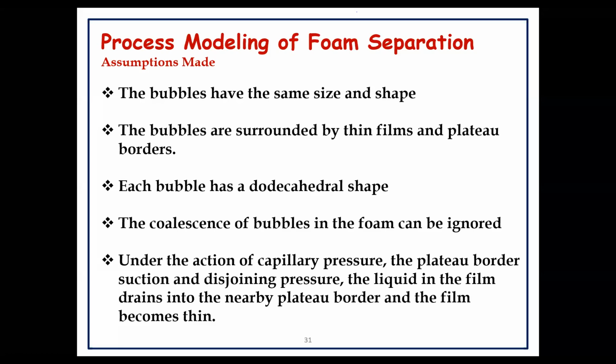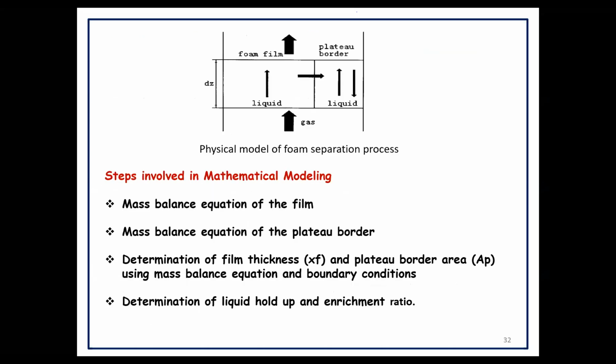The structure of the foam is very important to analyze, to do mathematical modeling for framing differential equations. So we have made all these assumptions before going for the mathematical calculations. Each bubble has a dodecahedral structure. Earlier we said that when 3 bubbles club together we get one shape, and when 4 bubbles club together we get a different shape. So all those inequalities are neglected. We assume that all the bubbles have a uniform shape and structure, and the coalescence of bubbles is ignored. These are some of the major assumptions made in the derivations, which cause some difference between the experimental value and the mathematical modeling. So we have to put a material balance equation for the film and a material balance equation for the plateau border.